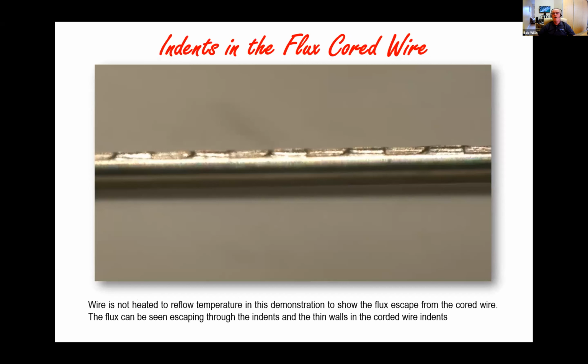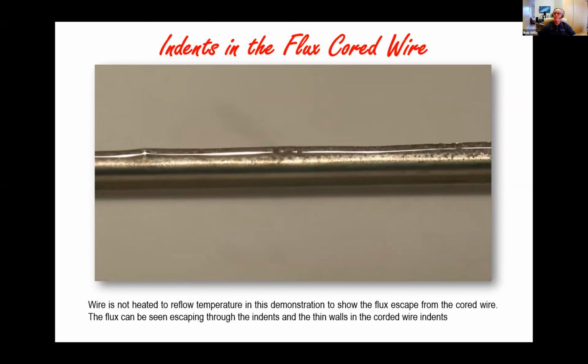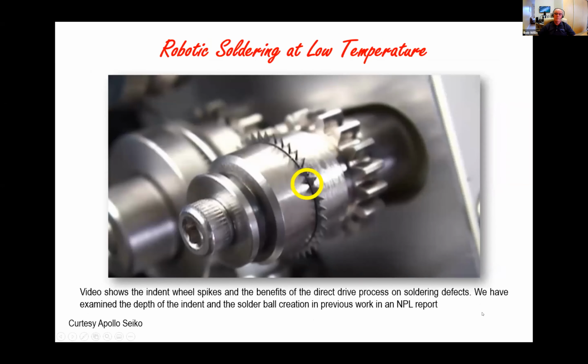And one little experiment that I conducted just to demonstrate this, here's some solder wire sitting on a flat sheet. I'm heating up the wire. And if you watch very carefully, you can see the flux come out of the core because of the indents, and that energy is escaping when there's not too much pressure. If it escapes too quickly, that's when we actually generate solder balls.